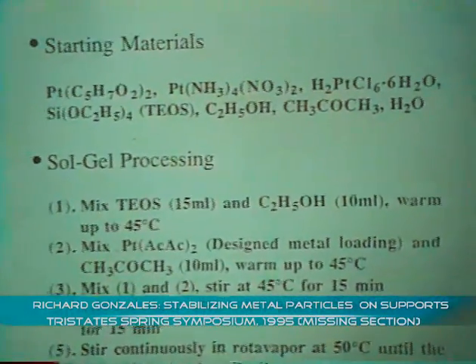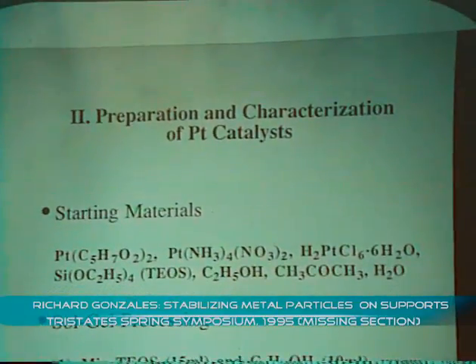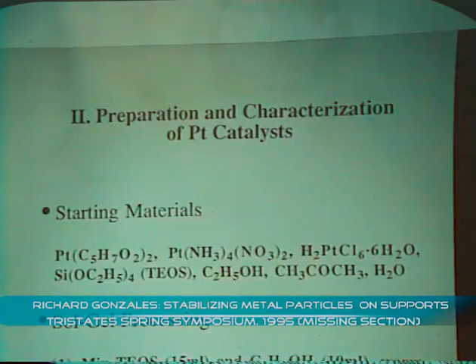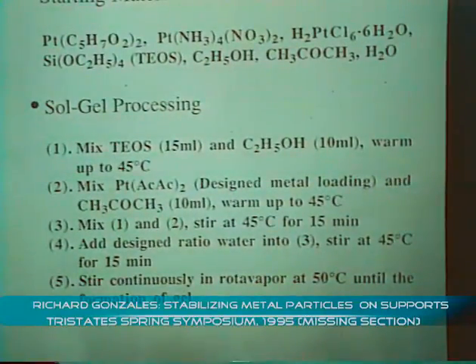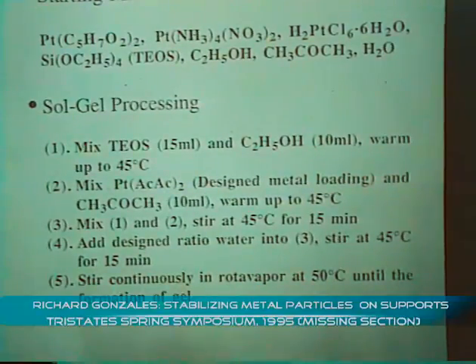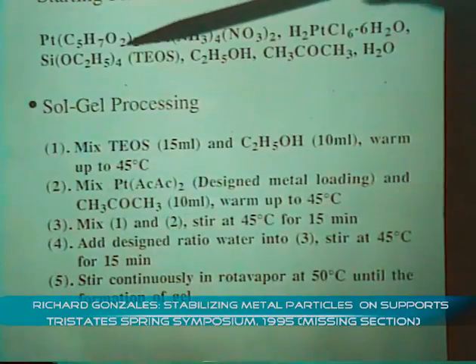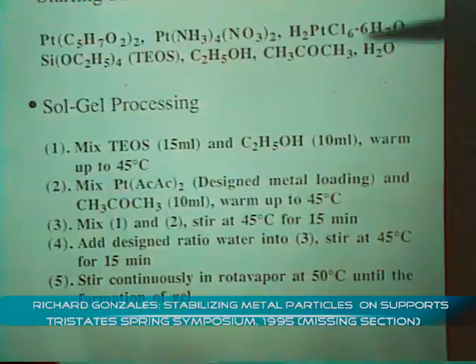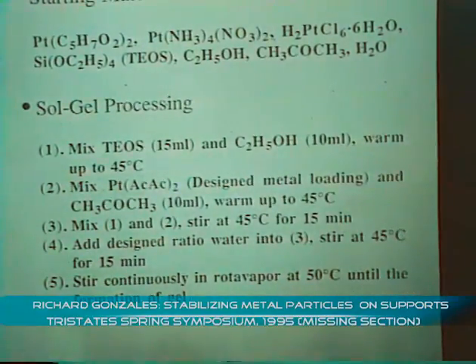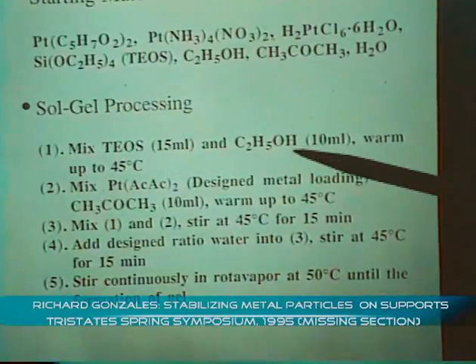Supported metal catalysts have been prepared by a variety of methods, most of which involve impregnation and ion exchange. Our synthesis is a little bit different. We used the sol-gel approach in which we have a one-phase preparation. We started with a homogeneous solution that includes the metal precursor, the support precursor, and the reagent, which is water, which tends to form the gel, which then can be dried to give you the supported metal catalyst. The synthesis is very simple. As precursors, we used platinum acetylacetonate, the tetramine, the chloride. And as the silica precursor, we used primarily tetraethoxysilane.